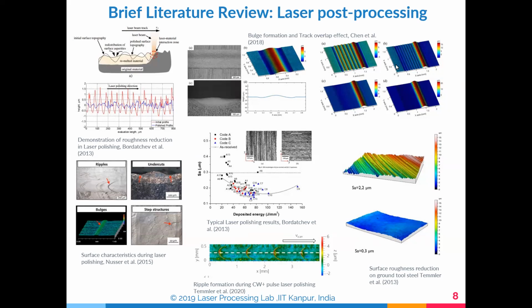You will get these A, B, C, D. All these are tracks which are used. So code A, code B, code C, all as received. Then we have Sa, surface roughness, and then the surface area. This is the deposition energy, which you can see predominantly happening here. This is before polishing and this is after polishing. Here you will have laser typical polishing results, and then you get the surface finish.